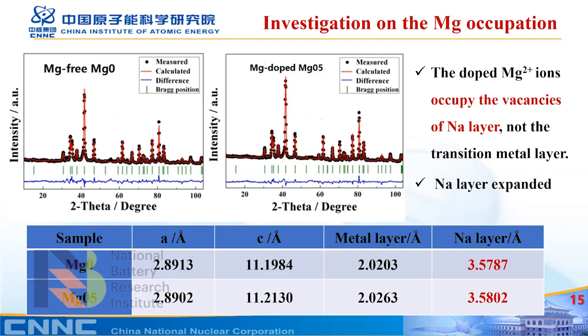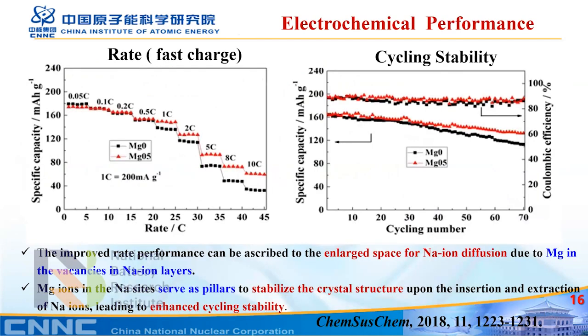So according to the electrochemical performance test, which we can also do in our lab, the capacity at high current densities improves significantly. This can be ascribed to the enlarged space for sodium ion diffusion due to magnesium in the vacancies in the sodium layer. The second conclusion is the cycling stability also increased a lot, as shown in the right figure. This is due to the magnesium ions in the sodium sites serving as pillars to stabilize the crystal structure during charge and discharge.